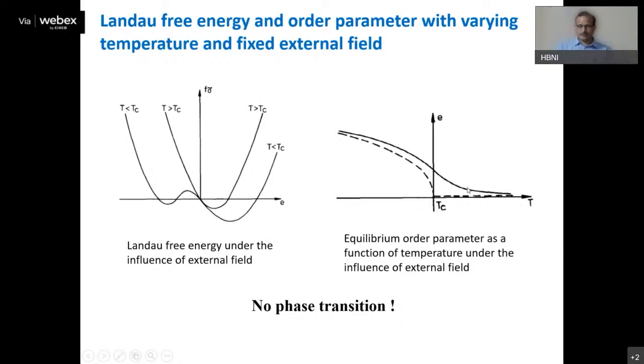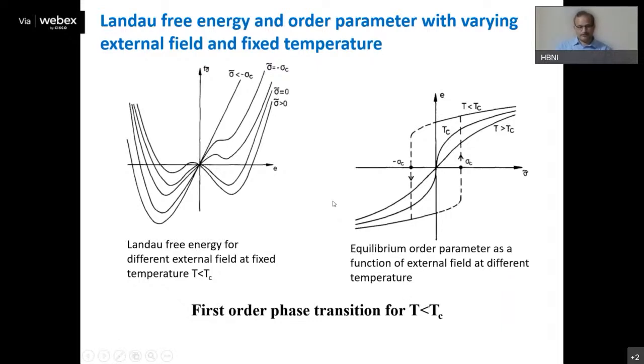So what essentially this means is that there will be no phase transition if you have an external field and the temperature is higher than Tc. Now consider the other case, when you apply a field below Tc. This is depicted here. This is the free energy in case there is an external field. You can see when there is no external field, you have a symmetric Landau free energy curve, similar to what I showed earlier. But as soon as you change this field, you start getting some dip. And these dips basically correspond to a discontinuous change in the order parameter value.